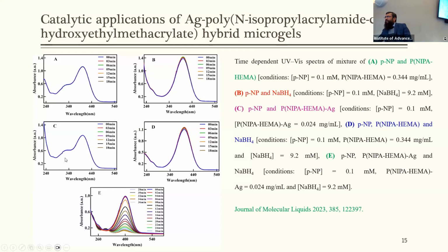Similarly, we also conducted another controlled experiment using p-nitrophenol as the substrate with the pure microgel and sodium borohydride, but we were not able to reduce p-nitrophenol by sodium borohydride in the presence of pure microgels. At the end, we used the hybrid microgel system as a catalyst to reduce the p-nitrophenol by sodium borohydride, and we were able to reduce the p-nitrophenol into p-aminophenol.